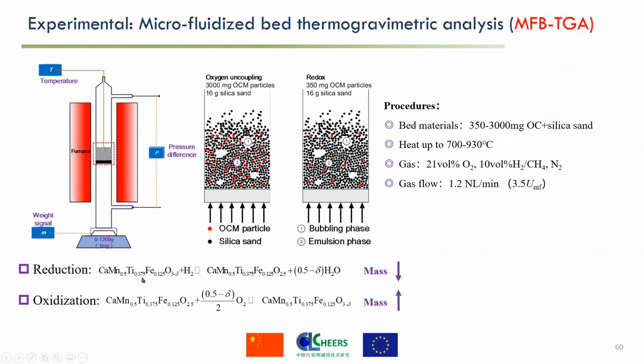During the reduction, CMTF will lose oxygen and its mass will decrease, whereas in the oxidation, CMTF gets oxygen and the mass increases. So the principle of MFB-TGA is to measure the real-time mass change during the gas-solid reaction, using a high-precision mass transducer to obtain the reactivity and kinetics at fluidized states. And then we obtain its reactivity at different temperatures and with different gases.